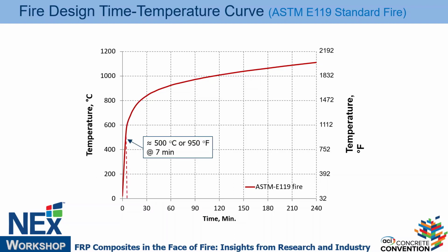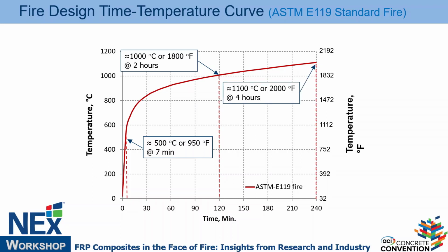And you can see here, I mentioned earlier, within 7 minutes you can hit 500 degrees, right? That's the standard temperature in the fire, right? And if you have something external, it may ignite if this temperature exceeds its ignition temperature, let's say. At 2 hours, 120 minutes, close to 1,000 C, which is 1800 Fahrenheit, and then after that it really doesn't increase significantly, going to close to 2000 Fahrenheit or 1100 C by 4 hours.